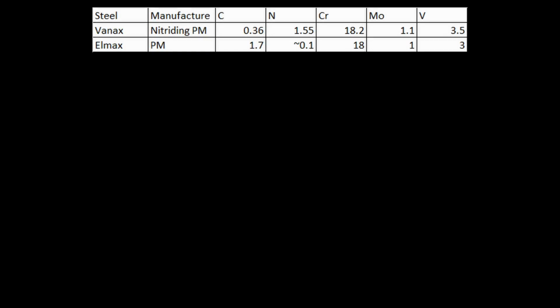All right, so let's move on to Vanax and Elmax. Again, these are two steels where I think people don't really connect them in their minds. They're both Uddeholm grades, so you'd think they would, but these are essentially the same steel. But Vanax replaces a bunch of the carbon with nitrogen. They both have 18% chrome, 1% moly, and around 3 to 3.5% vanadium. So basically the same steel, but one has a bunch of nitrogen in it.